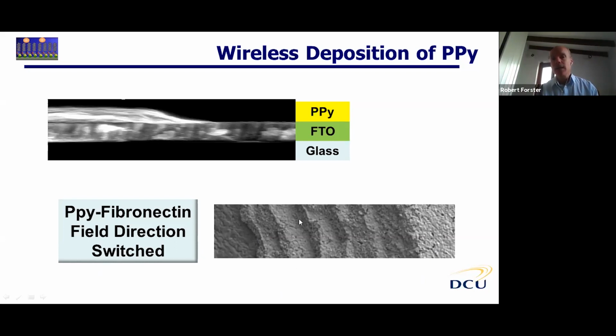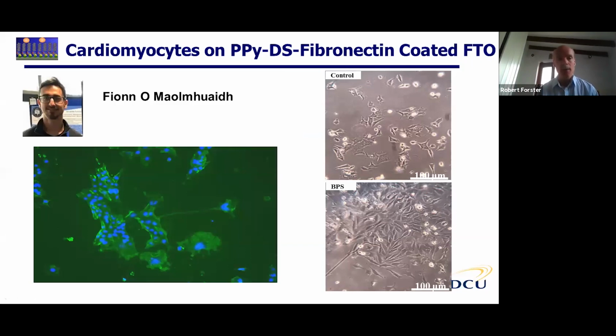What you actually get are these bands of growth within the polymer film, so you go from a smooth wedge-shaped film to one that contains bands in the pulse situation. Again, you can control the potential dynamically in time on this bipolar electrode, and use that to control the structure of the conducting polymer.